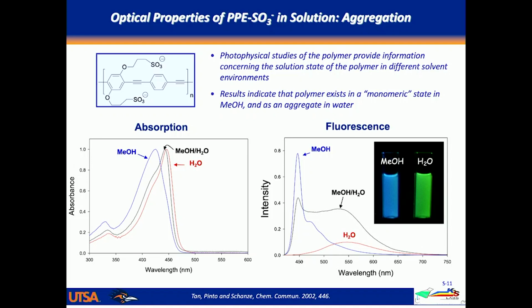And Chunyan Tan was studying this polyelectrolyte just in terms of its fluorescence properties, and she found quite an interesting effect that at first we were a bit confused by. And the easiest way to think about it is just to look at the color of the fluorescence by eye. In an alcohol solution, the polymer is blue fluorescent, and it appears as this structured emission band. And for those of you who know something about conjugated polymer photophysics, you would recognize that as being a typical fluorescence for a conjugated polymer, meaning that the Stokes shift relative to the absorption, which is in the blue, is pretty small. So it looks like what you would expect for this family of polymers.